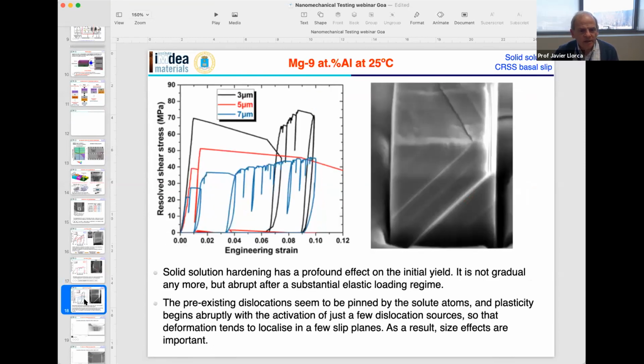So this is the case for a magnesium alloy that has 9 atomic percent of aluminum. This has been tested at 25 degrees Celsius. And these are the resolved shear stress versus engineering strain curves. And as you can see here, for the very small micropillars, you have a linear behavior, and then you have the localization of the deformation in strain bursts.